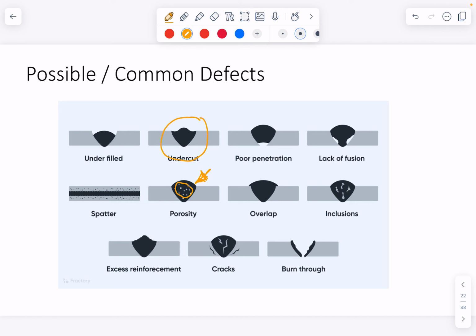Undercut is, again, a defect, and it causes a problem, again, with stresses because you've reduced the thickness. There's a lower thickness through where that undercut is. And that undercut can either be in the weld, but it can also be in the area adjacent to the weld. And so you might have the weld metal built up enough, but you've undercut the parent. And therefore, again, you've got a lesser thickness to deal with the stress, as well as a stress concentration because of the shape of the thing, etc.